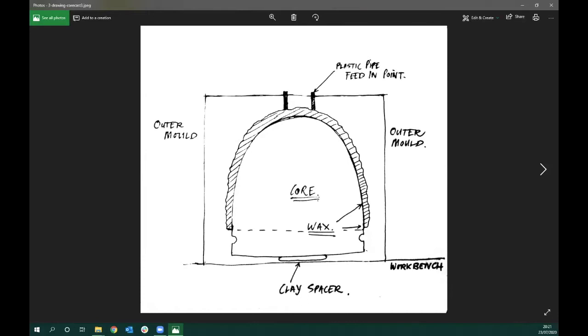So in order to get the outer mold to surround completely the inner core, we set it up on a little clay foot on top of the bench so that the outer investment mold can completely surround that inner mold, trapping it inside so it can't go anywhere, it can't float. And then you see at the top there's this little feed-in point. That's important for getting the glass to flow into the form.